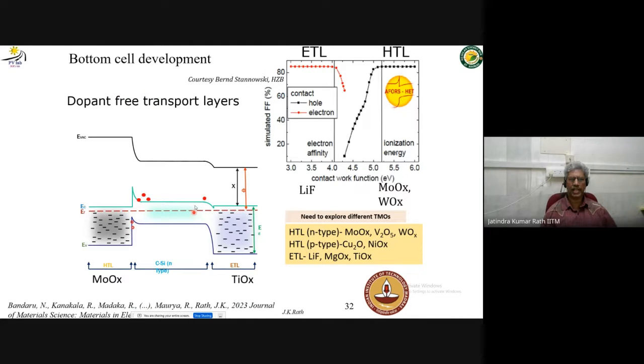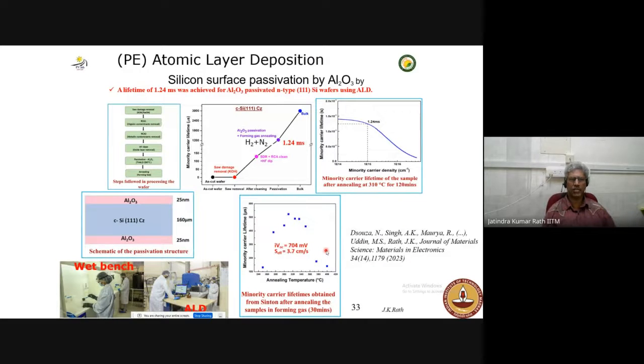To do that, you can see here, the cartoon that's going on. You have a lot of hole transport layers, like molybdenum oxide, vanadium oxide, tungsten oxide, and electron transport layers, like lithium fluoride, magnesium oxide. The only thing is, the ETL layer should have a small work function, whereas the HTL layer should have a high work function. That's what is needed. Once that is done, the electron holes are formed here, and they will be collected at different contacts. This is the electron transport layer and hole transport layer, so it will be connected across it. And we have already made this sort of layers, and one more thing needed is the passivation surface.